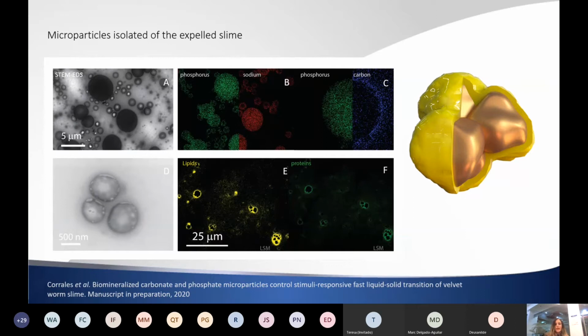Also, when you do TEM, you don't have to coat the sample with gold, because if a sample has phosphate, you will confuse the peaks with EDX. So we could see that what the animal has are all these particles that are sodium phosphates, basically. We see here, for example, this globule is based on phosphorus, on sodium, and it also has this carbon coating. And this carbon coating is a lipid and a protein. So the inorganic salts are stored in these vesicles that are lipid proteins.